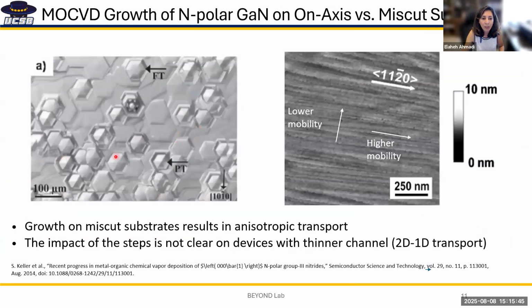So going back to MOCVD, for nitrogen polar, if by MOCVD we grow on-axis substrate, and this is something Stacia Keller at UCSB has worked on, she showed that basically these hexagons form when you grow on-axis. And what she developed was this growth on miscut substrate, and she showed that with growing on 4 degrees miscut, we can get robust APS structure with no hexagonal hillocks.